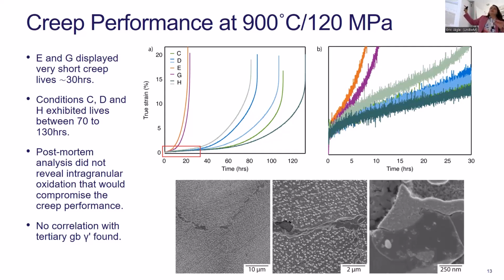And it kind of shows you the variation in the method that we use to test the creep. We've got about 30% variation in the methodology itself. So we get lives of 70 to 130 hours, right? We were aiming for about 100 hours. So we are within that range, which is great. The two that stick out considerably as being very, very bad are E and G. Yeah, and they had creep lives of 30 hours.